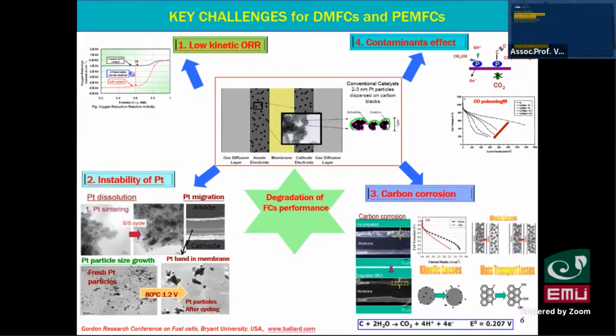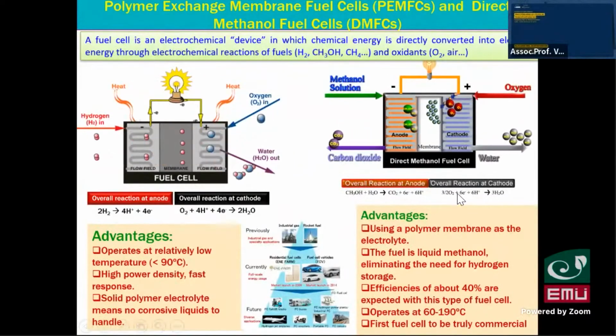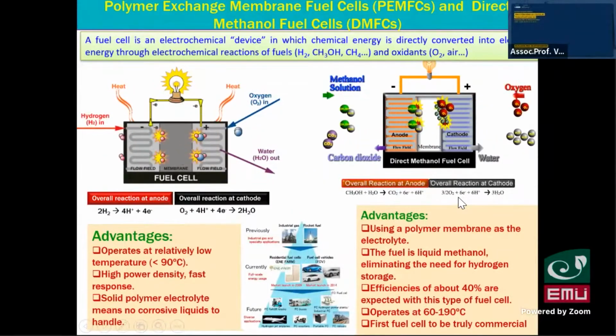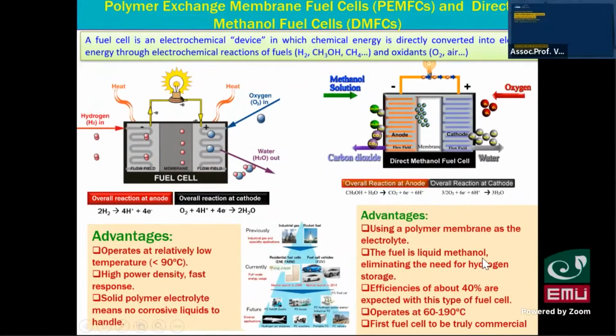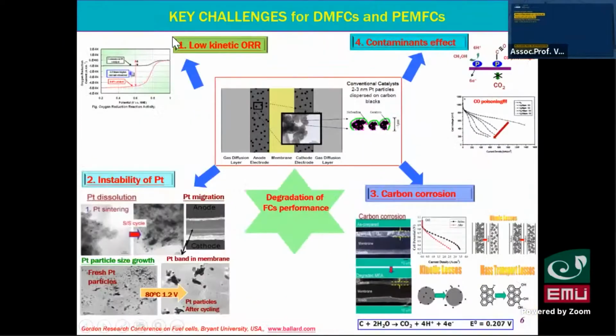So the first current issue is the low kinetic ORR, the oxygen reduction reaction at the cathode. You can see here at the cathode, the oxygen will be reduced. So this is the problem of low kinetic ORR, and this problem will cause the efficiency of the fuel cell to break down.